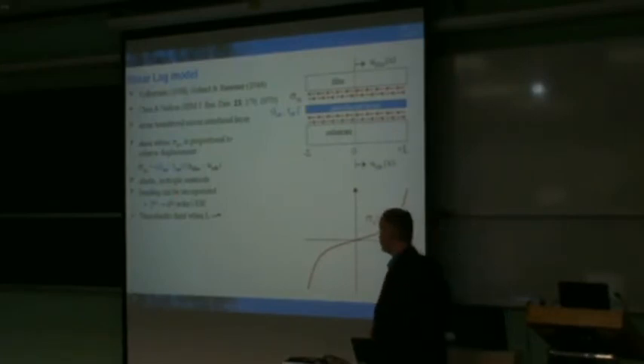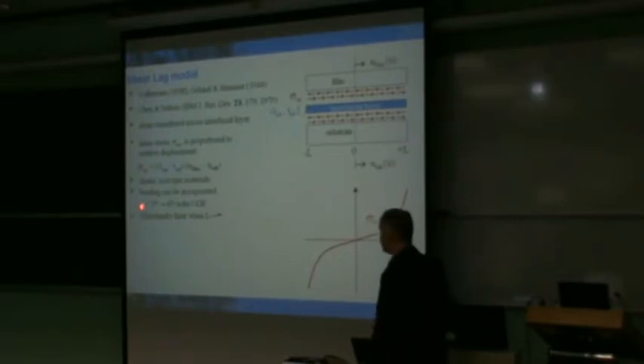Now there are other assumptions that go into this type of approach. One is that we're dealing with linear elastic isotropic materials. The first implementation of this only looked at the effects of normal stress in the plane here. And so this actually is very simply solved by second-order ordinary differential equations. So very simple to implement. You can actually extend that a bit to consider the fact that since we know that these substrates do warp due to the presence of these overlying blanket films and film features, that we can think about the bending and the deformation that exists in the vertical component.